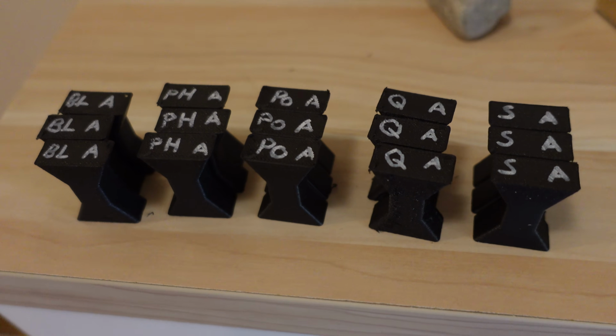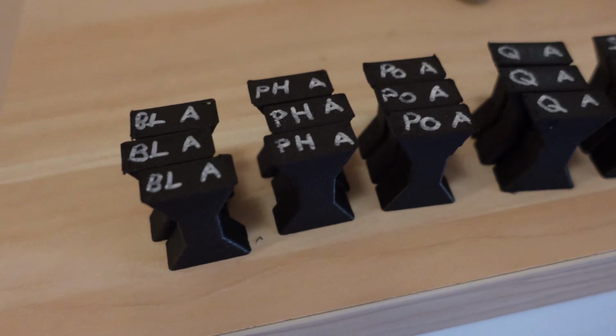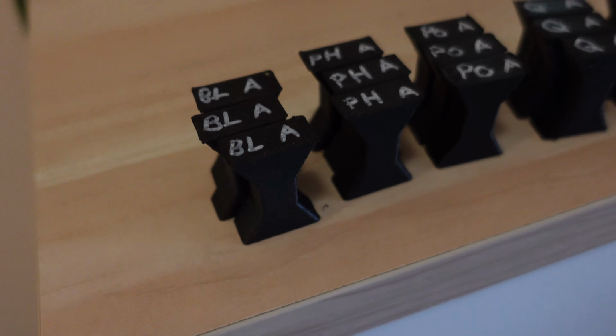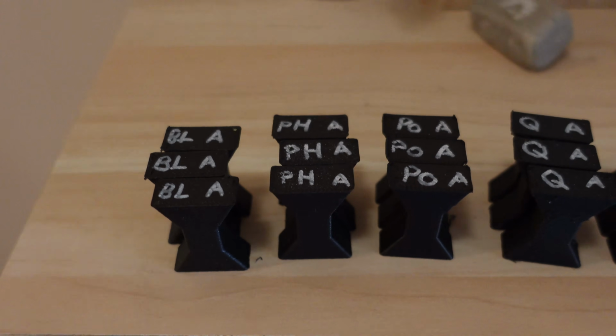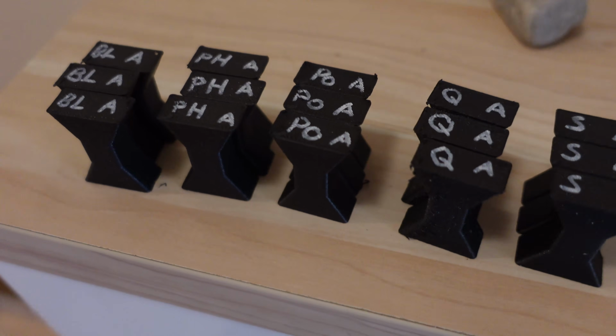It is good to see that BambuLab printed on default settings is not much weaker compared to the printing on 270 degrees Celsius, but basically in all 6 cases this is a good layer adhesion. Still the layer adhesion, but these are printed on BambuLab A1 on Open Printer. And one thing I noticed on Open Printer, I don't have so constant results, but we will find out that soon.